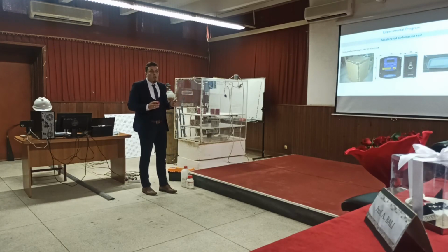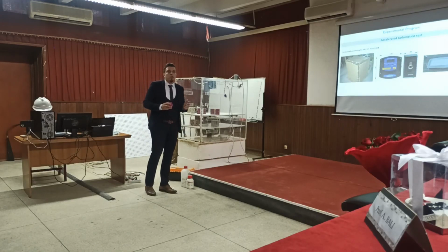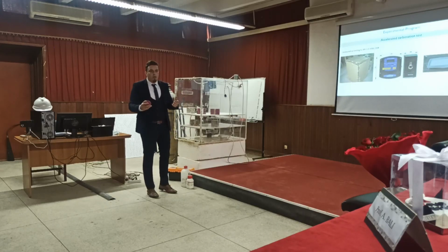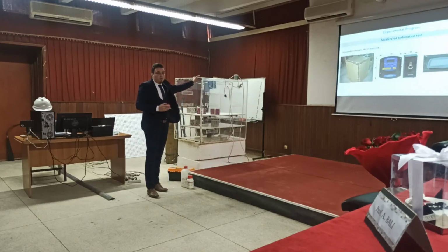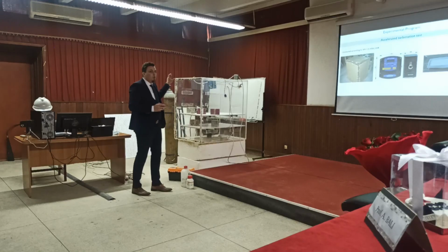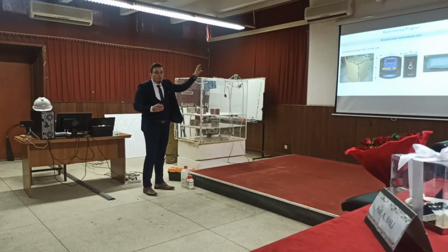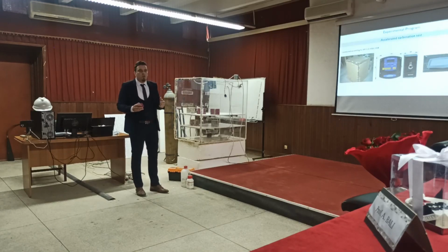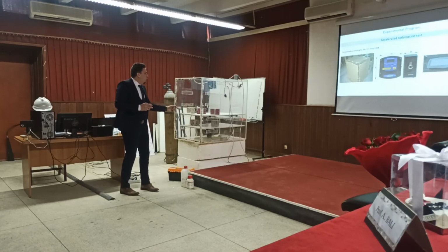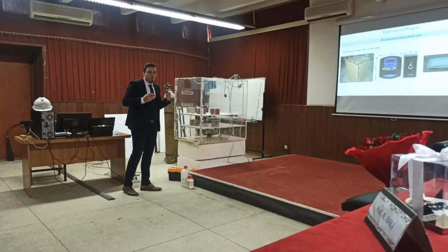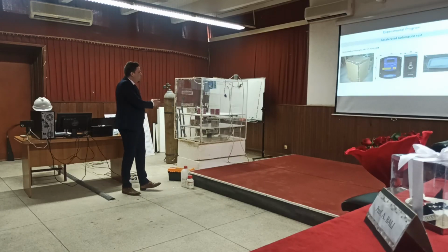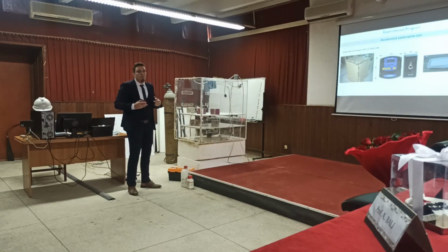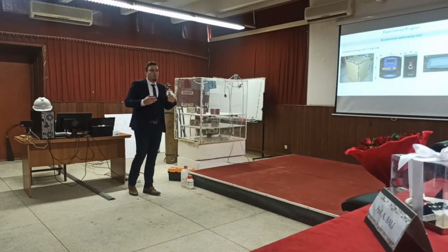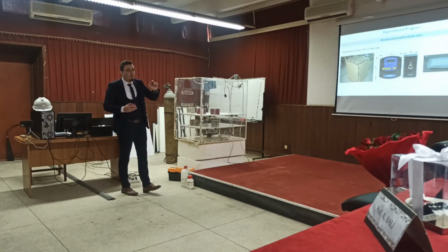Now, arriving to the first challenge that we faced in our experimental program, which is the accelerated carbonation test. We didn't have an accelerated carbonation chamber, and we were obliged to manufacture our own. In order to manufacture our experimental device, we spent 2 years learning all the conditions and requirements following the standard, which is the French standard. And in order to put as many specimens as we can, we built it with a big volume. This doubled the difficulty of our work.